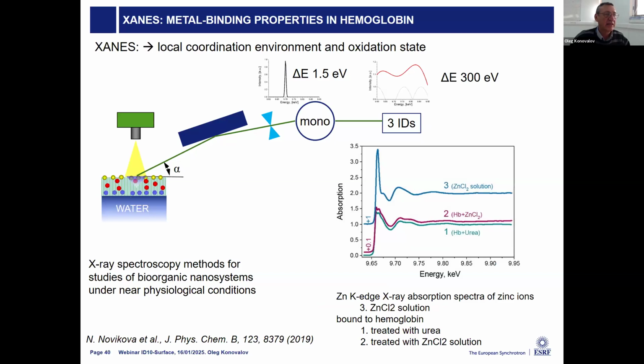And about X-ray absorption measurements, which recently we start to apply more and more often, so then we can see electronic states. In this example, we followed the zinc atom, and we see how this metal binds to the hemoglobin and how it changes the coordination of the zinc, depending on the type of pure solution or solution treated in different ways with zinc.